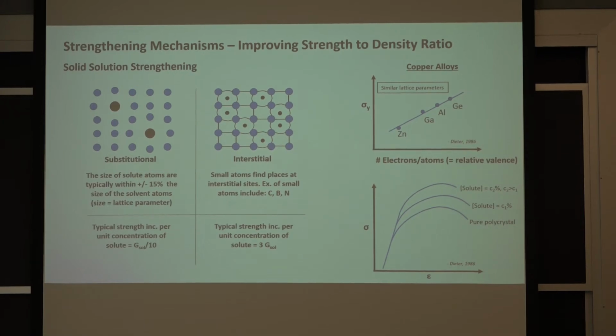Now, whether you're putting an atom at a lattice site or at an interstitial site, it creates a distortion in the lattice structure. That distortion is enough to impede a dislocation from moving through the material. So that's a way to increase the strength of the material. As a general rule, through substitution, you can increase the strength of a material by the shear modulus of the solute material divided by about 10. That's an increase in strength. And for an interstitial material, you can increase the strength by about 3 times the shear modulus of the solute atoms. So from both of these you get an increase in strength, but from the interstitials you get a bigger increase in strength.